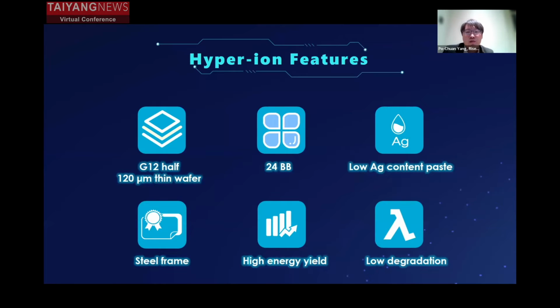And the third one is we are using the low silver content paste to save the metallization cost. In this case, we can achieve very low cost metallization level and achieve roughly 10 milligram per watt pure silver content. Number 4 is we are using steel frame. There are 2 advantages. First one is carbon footprint is lower than aluminum frame, and the overall stiffness of aluminum frame can meet the demand, but the local stiffness is weaker. So we think steel frame is very good product to integrate with our heterojunction cell.